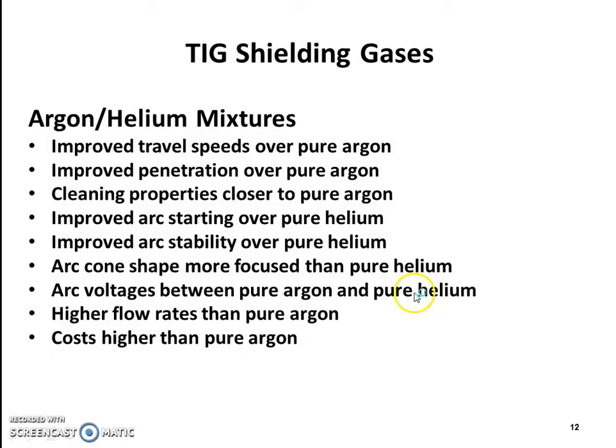Argon-helium mixtures: improved travel speeds over pure argon. Improved penetration over pure argon. Cleaning properties closer to pure argon. Improved arc starting over pure helium. Improved arc stability over pure helium. Arc cone shape more focused than pure helium. Arc voltages between pure argon and pure helium. Higher flow rates than pure argon. Cost higher than pure argon.